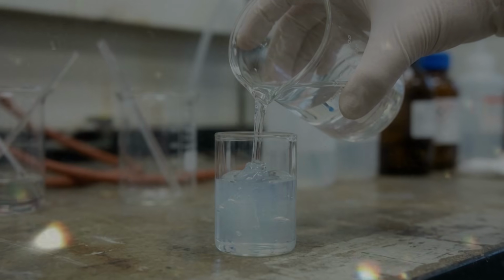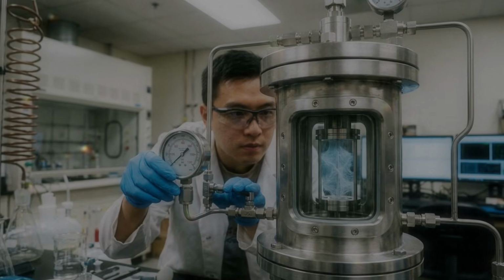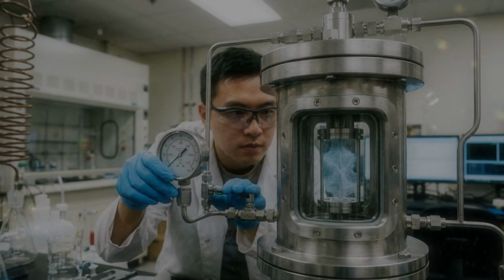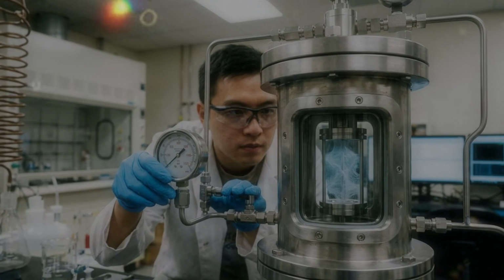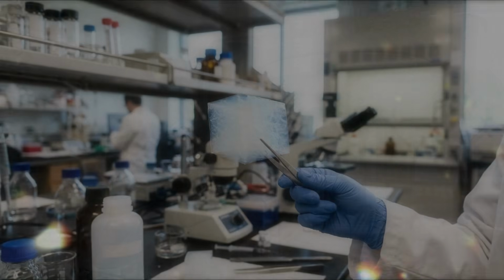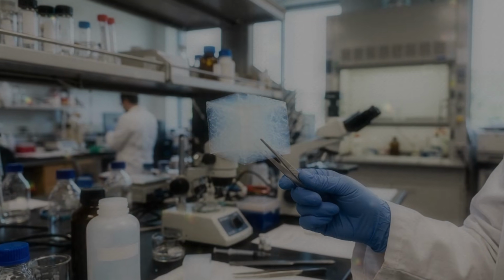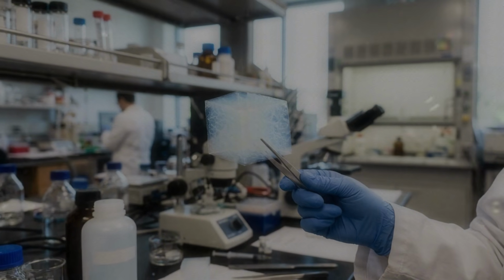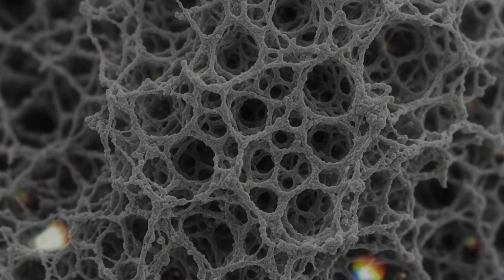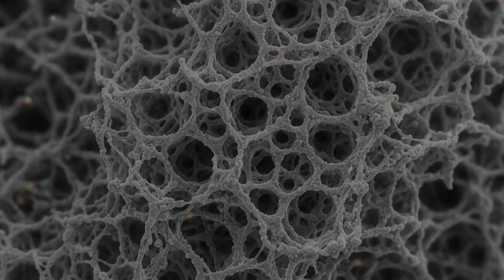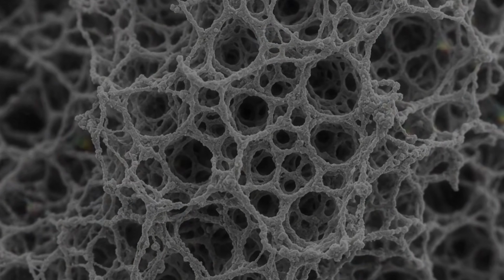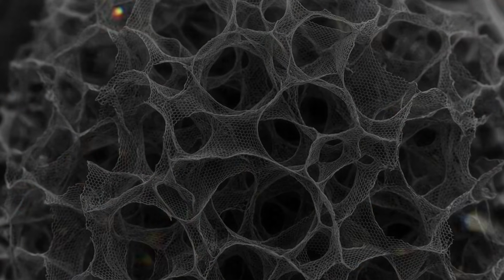Electrical performance changes when the aerogel is compressed. As the pores close, more carbon sheets touch. New paths appear and the resistance can fall. When the pressure is removed, some contacts separate and the resistance rises again. This change turns the material into a sensor. A small force applied to the surface creates a measurable electrical response. The greater the pressure, the more the structure changes.